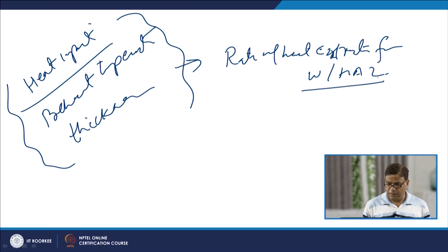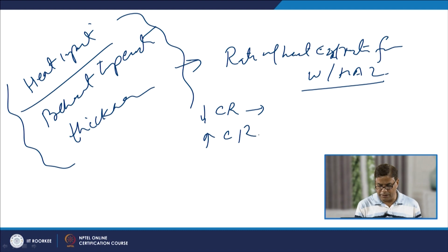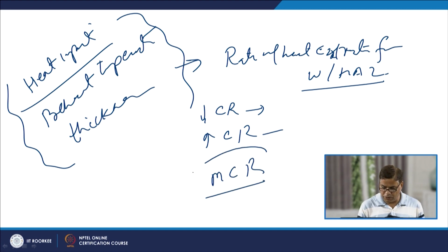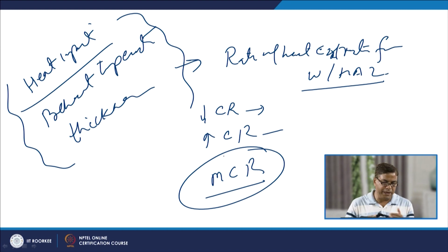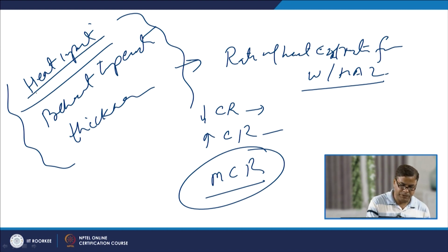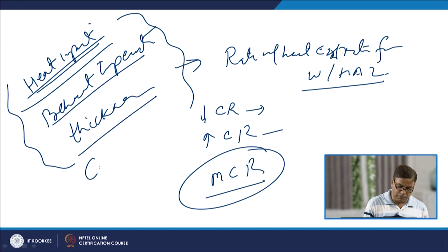So, what we have seen earlier, that if the cooling rate is very low, then we get the unfavorable structure. Similarly, if we have very high cooling rate, then again we get the cracking tendency due to the formation of untempered martensite. So, we need to have the moderate cooling rate, and the moderate cooling rate can be realized by having proper consideration to the heat input, preheat temperature and the thickness for a given composition of the steel.